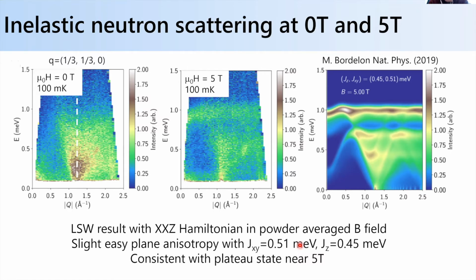It's just hard to grow any crystals of it. But instead, if you go to sulfide or selenide or telluride, you can get single crystals, and then you can get sharper phase diagrams. And there is an anisotropy between the field in plane and out of plane, which is quite large. But for some reason, it's just not obvious in the powder. I don't fully understand it. Thanks. Yeah.